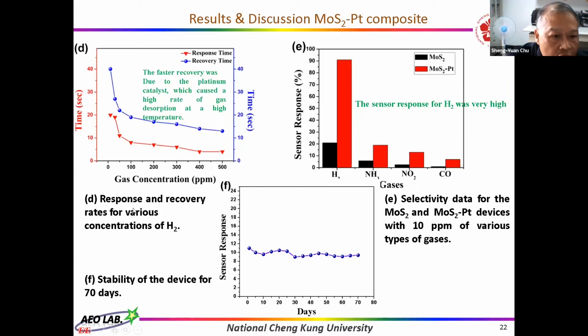Figure D shows the response and the recovery rates for various concentrations of hydrogen. We can see the fast recovery was due to the platinum catalyst, which caused a high rate of gas desorption at a high temperature. And also, in this figure, the sensor response for hydrogen was pretty high, and the black one is for the MoS2.